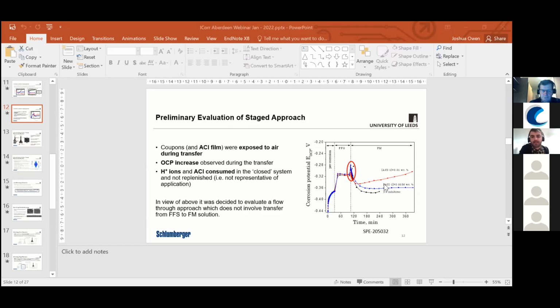Yeah, so again, the inhibitor concentration has an influence on corrosion potential. Depending on the type of inhibitor used, it can fluctuate either anodically or could stay the same in some conditions. Generally, the high concentration that we use shifts it more anodically in this case, but it also depends how effective the inhibitor actually is in that environment.